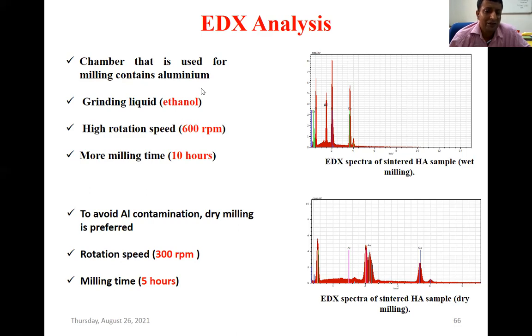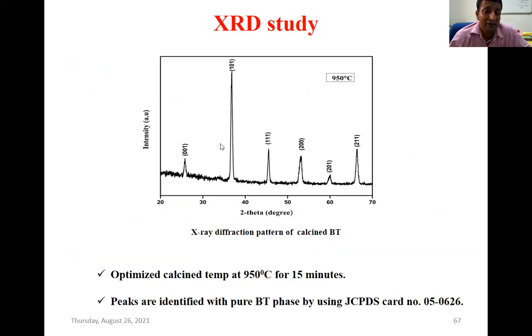So that is what we did, the dry milling. We didn't use the media, and we reduced the rotation speed and the time duration also. With that, the aluminum peak should have been there, but it was not there actually. We got rid of these impurities.